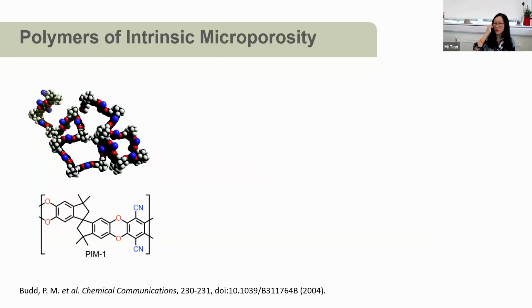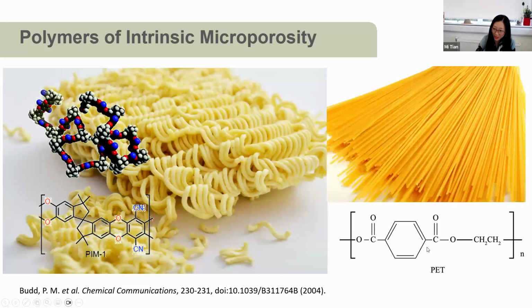So therefore, we found the polymer of intrinsic microporosity. You can see the molecular structure of PIM1. PIM1 isn't like the traditional polymer. Traditional polymer has a long linear chain, which can be packed efficiently, so there's no voids. PIM1 is very special. It's got this rigid, contorted angle here, which cannot be packed efficiently, leaving a lot of voids in its long chain. So that is where the porosity comes from.